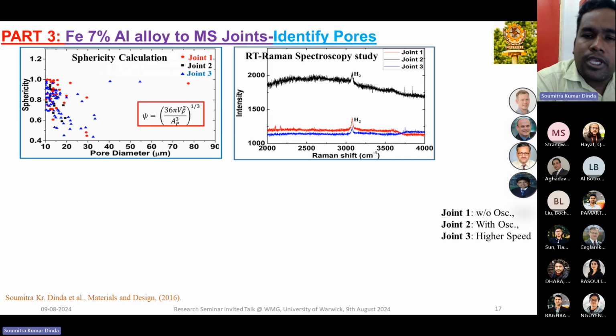Then the question will come: from where does this hydrogen gas come, because we are doing welding at a very high vacuum? This hydrogen may come from within the material during the casting process. Otherwise, when we are mechanically putting the material together before putting it into our vacuum system, some gas pocket or air pocket may enter. And we found only hydrogen gas is responsible for the gaseous pore formation.